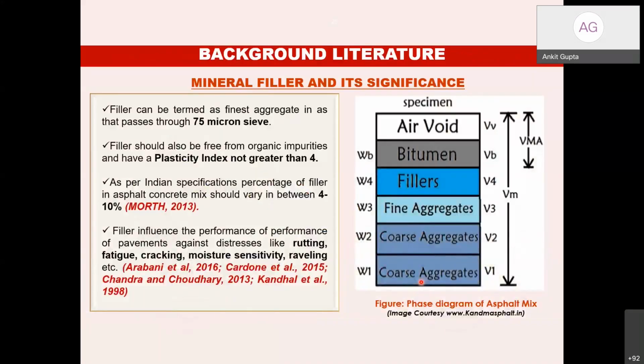Okay, now coming to the mineral filler, those who are not aware of this area can try to understand that fillers are the finest aggregate which is passing through the 75 micron sieve. Now, our codal provisions, the Ministry of Road Transport and Highways provisions, say that a filler should have two properties to be used for our pavement construction. So the first one is the filler should be free from organic impurities and have a plasticity index not greater than 4. So if the PI is less than 4, it can be used as a filler in our pavement industry. The first thing is passing through 75 micron. Second thing is PI less than 4.